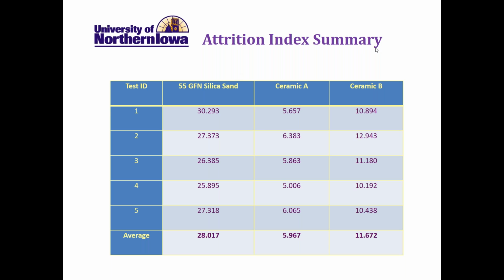If we take a look at it in tabular form, we can see that the attrition index in the silica was 28 grain fineness numbers. In ceramic A, less than 6, and ceramic B a little more than 11.5. So major improvements in the breakdown of those sands.